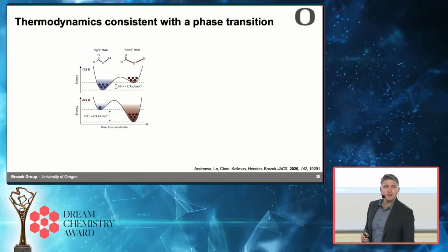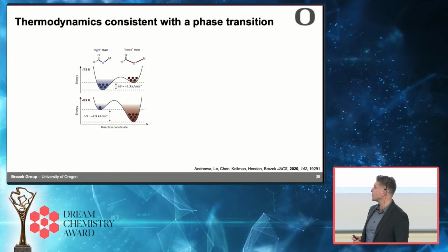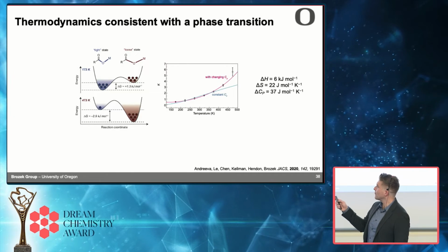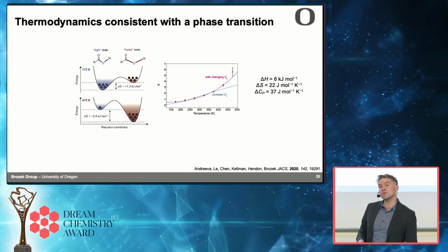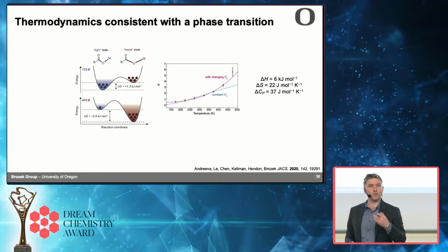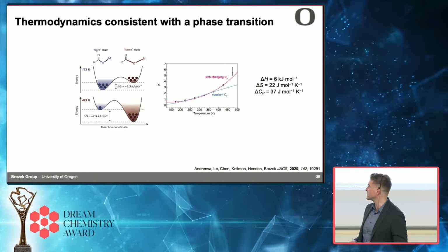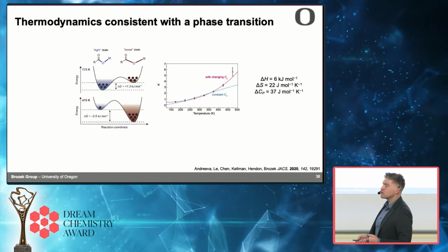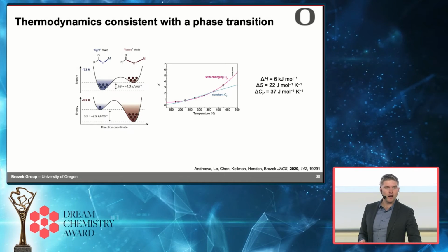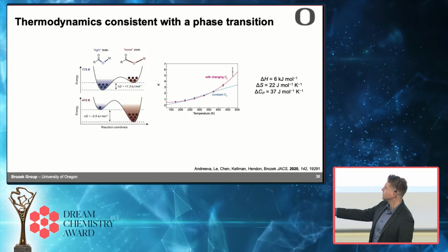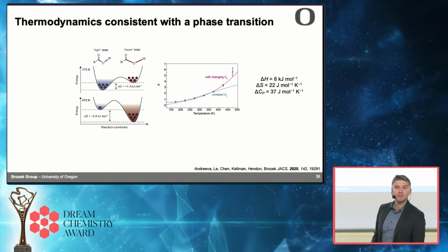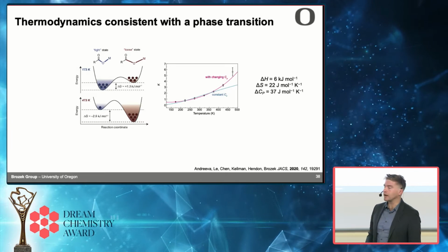Okay, so we have that data. We wanted to dig even deeper. So with equilibrium constants versus temperature, we should be able to extract out thermodynamic information about this process. And so we tried fitting the data to a typical Van't Hoff relationship. That's the fit in blue. And it was pretty lousy. We didn't really know why.